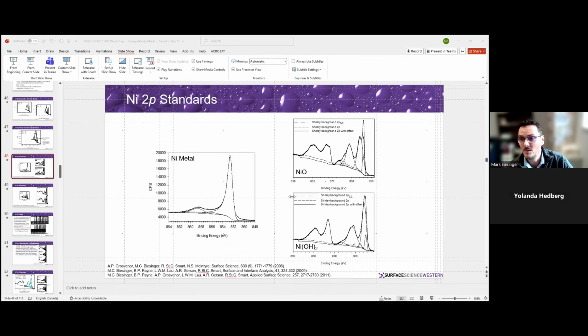So if you use magnesium or silver, you're moving those Auger peaks out of the way, and then the peak shapes that you get will be the peak shapes that you get. So that's a possibility if you can understand that you're going deeper into the material, and that might change things as you go deeper. But that's the easiest way, is to actually use a different X-ray source to move those Auger peaks, if it's available. Sometimes, or you need to find someone that can do that sort of thing for you.